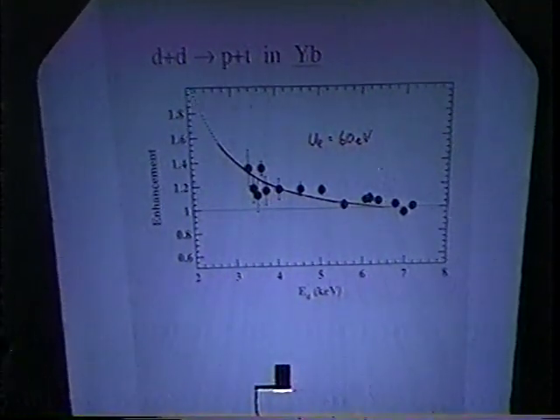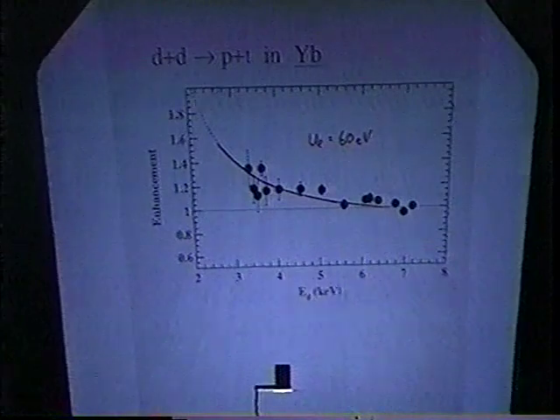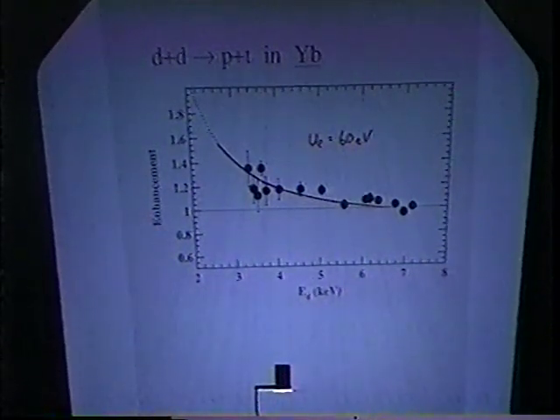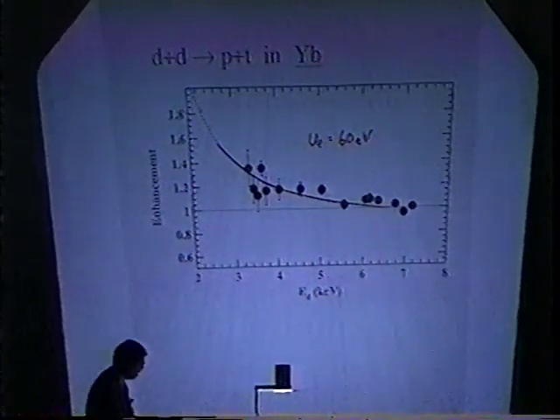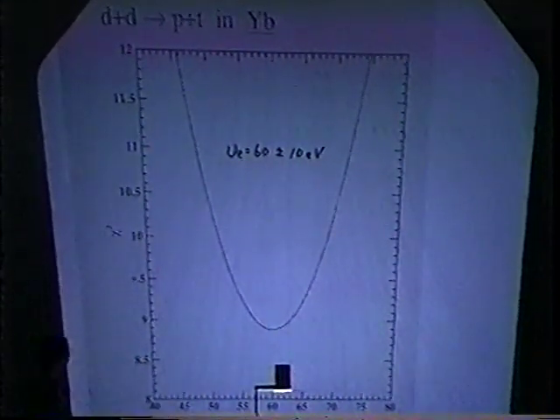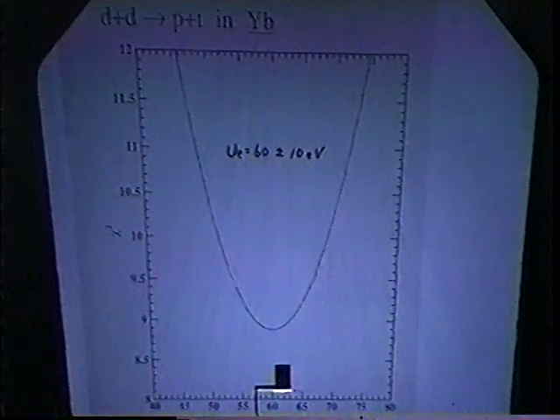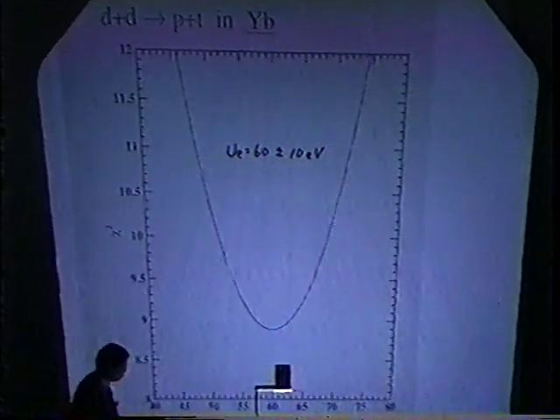If I plot the same way as I did for the titanium case, for the ytterbium case, the real enhancement occurs below 5 keV, and also the amount of enhancement is higher than the titanium case, something like 30%. And this red line corresponds to the screening potential of 60 electron volt. And also, I want to show the result of the chi-square test. It clearly shows the minimum value is something like 60 electron volt.